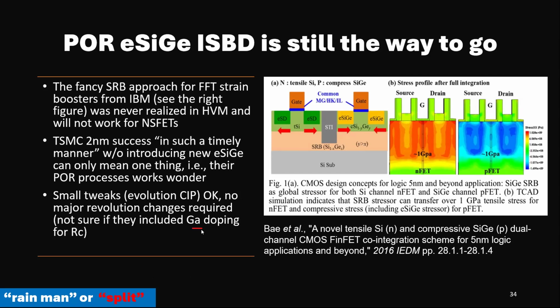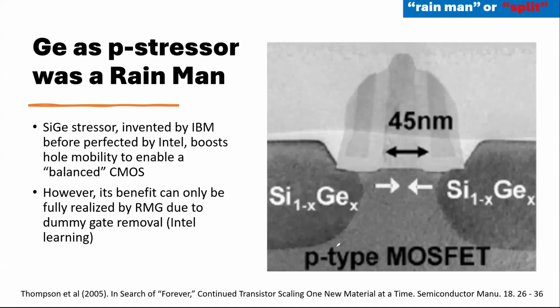It doesn't even include gallium doping for contact. This is critical, right? Because at the contact, you need very high doping. Gallium seems to help boron. People try that a lot, but I didn't see that, right? So that POR is so nice. They just use this process. It's good enough. Not exactly the same process because there's no E-beam film, the film does not have this diamond edge. They cannot have it.